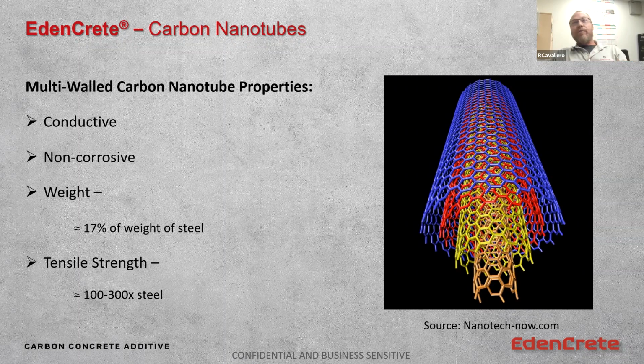Well, when we compare carbon nanotubes to steel, carbon is non-corrosive. They're inert. They're lighter. They're 1/6 the weight of steel. And when we look at the tensile capacity of 60 KSI steel compared to a carbon nanotube, the carbon nanotubes are anywhere from 100 to 300 times stronger in tensile capacity than steel.